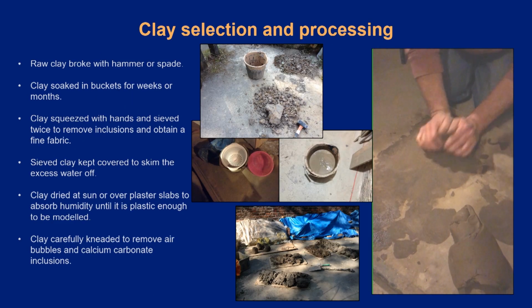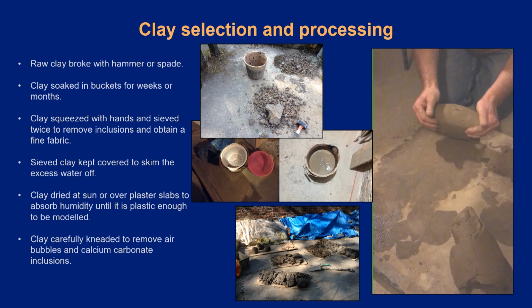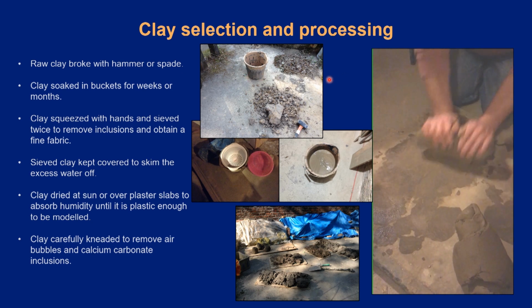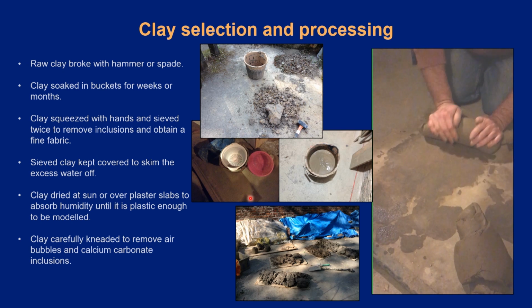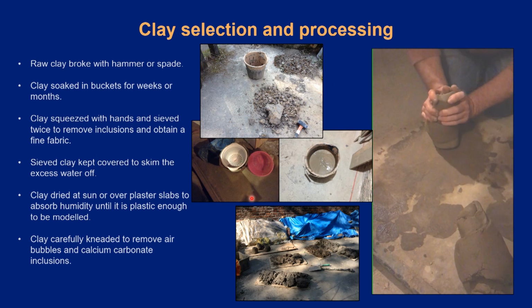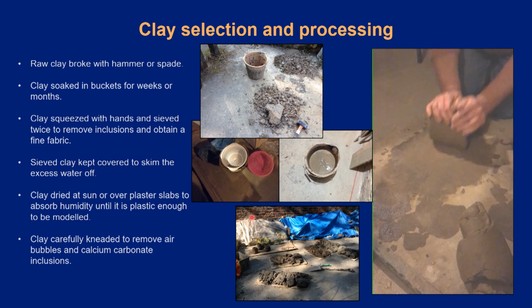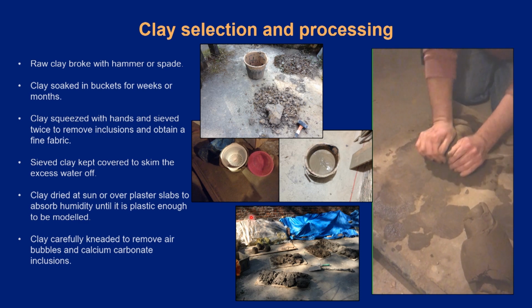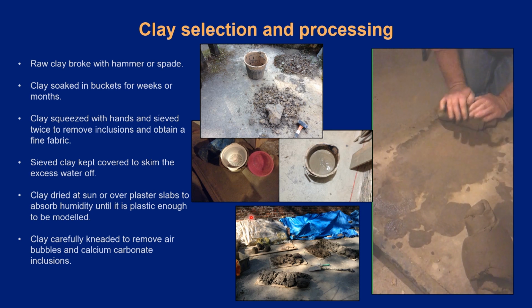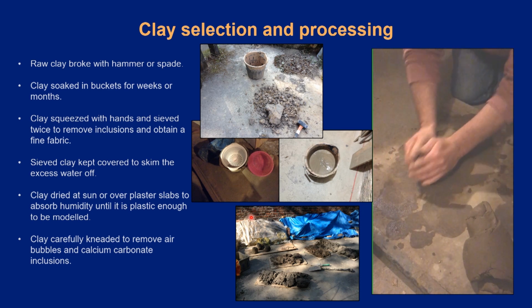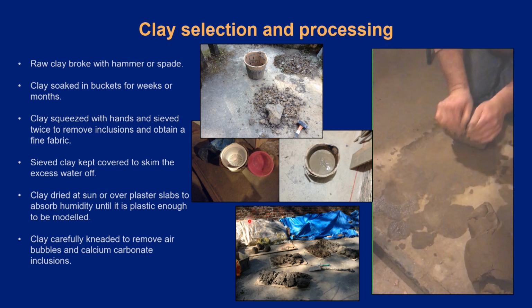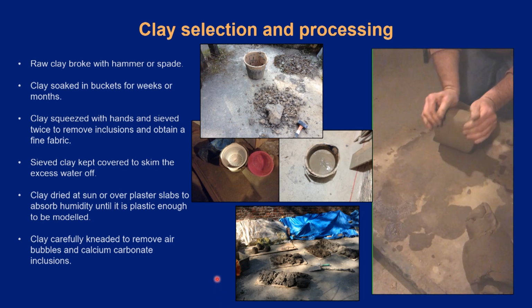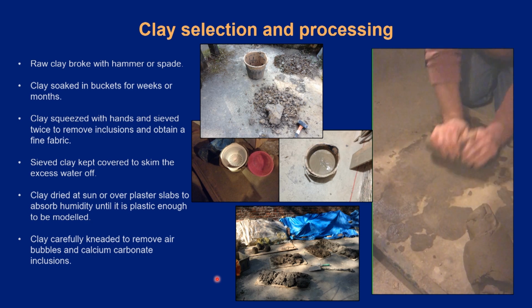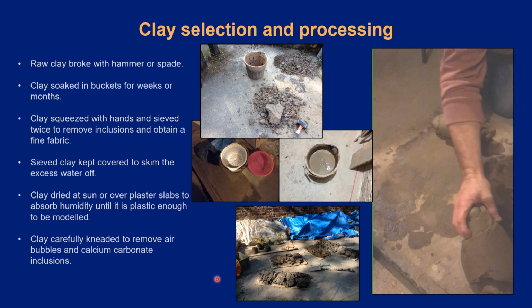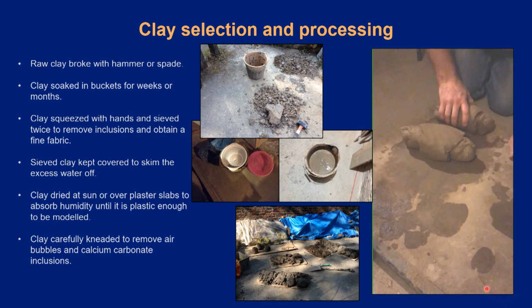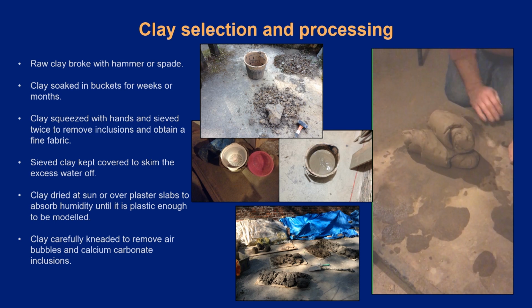To prepare the clay for the pottery, first of all we broke the raw local clay with a hammer or spade, and then we soaked it in buckets for weeks or months. Later the clay was squeezed by hand and sieved twice to remove inclusions and obtain a fine clay body. During the following weeks, clay was kept covered to skim the excess water. Then it was dried under the sun or over plaster slabs to absorb humidity until it was consistent enough to be modeled. Lastly, clay was carefully kneaded to remove air bubbles.